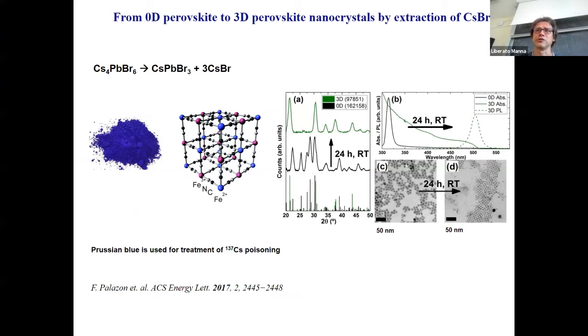The transformation is not as easy as just removing a fraction of the cesium bromide from a single nanocrystal. It's sort of a redissolution, recrystallization kind of reaction.